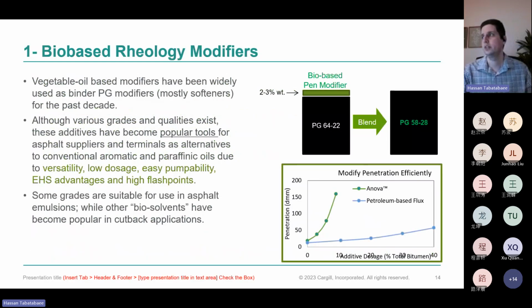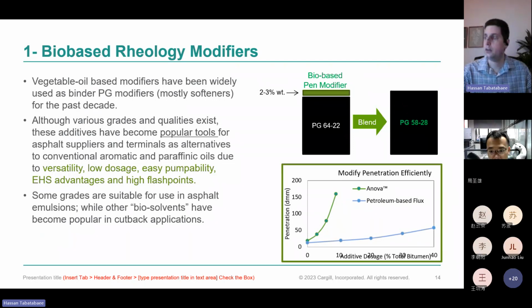So how are these used in asphalt? One of the methods that has been used the longest, although perhaps not as commonly known, is using bio-based modifiers to modify asphalt binder or bitumen. Quite often, these are very efficient replacements for using, say, aromatic distillates or other types of petroleum-based oils that are used to soften asphalt. Here you have an example showing performance grade modification for a PG 64-22 to PG 58-28. Only 2 to 3% by weight can take a full grade change. And for those of you familiar with the performance grading system, one grade shift of 6 degrees means cutting the viscosity about in half. So it's almost halving the viscosity there.